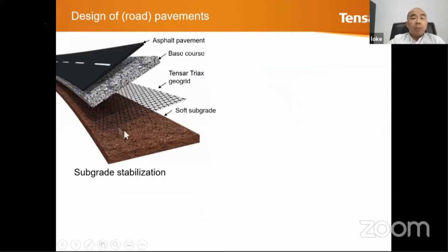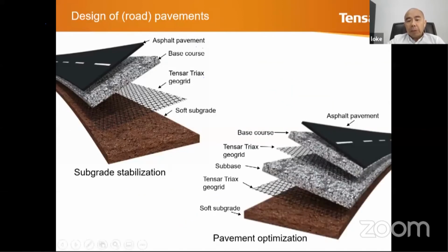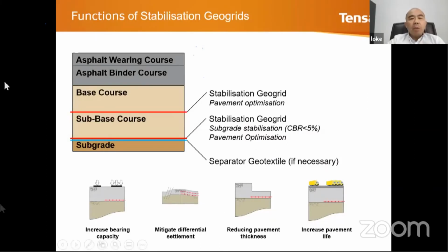So the new technology is that we put a layer of geogrids directly underneath the base course. Okay, so this is only one layer for subgrade stabilization. If you want to do a pavement design, we call it pavement optimization, then you will put 2 layers. In other words, one layer directly above the soft subgrade, and then the sub-base material, and then you put another layer of geogrids in between the base course and the sub-base material. Okay, so let's look at these two design mechanisms and how we do it. So that's how you put the geogrid: subgrade, sub-base, base course, a layer of geogrids here and a layer of geogrids here, and then you have your binder course or your AWC, which is the asphalt wearing course.